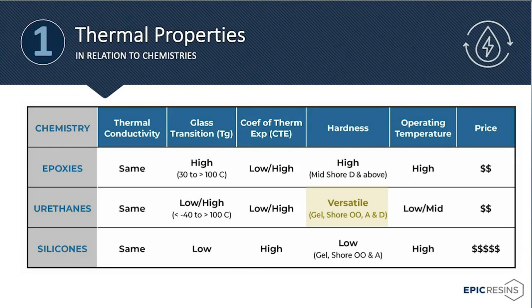We can range anywhere from a urethane having a low hardness, gel type of material, anywhere from Shore A to the D hardness. And then as we talk about silicones, generally those are lower gel materials or Shore A, again, because of their cross-link density. When we compare these three chemistries in operating temperature, epoxies have the ability to have high operating temperature, again, coming from its ability to have higher cross-link density.